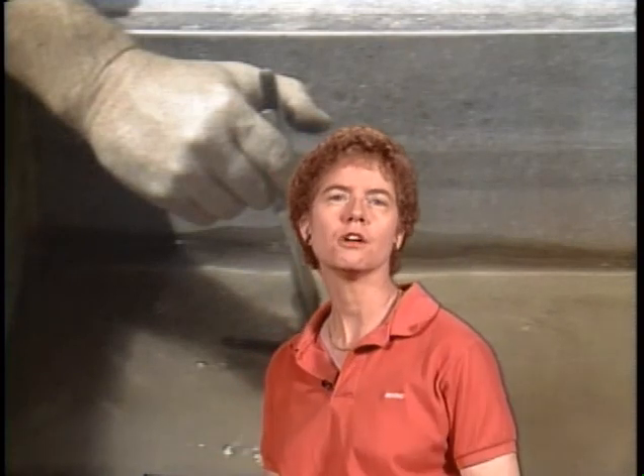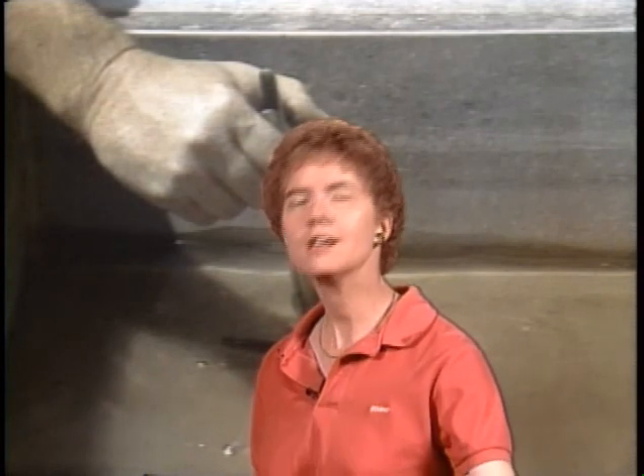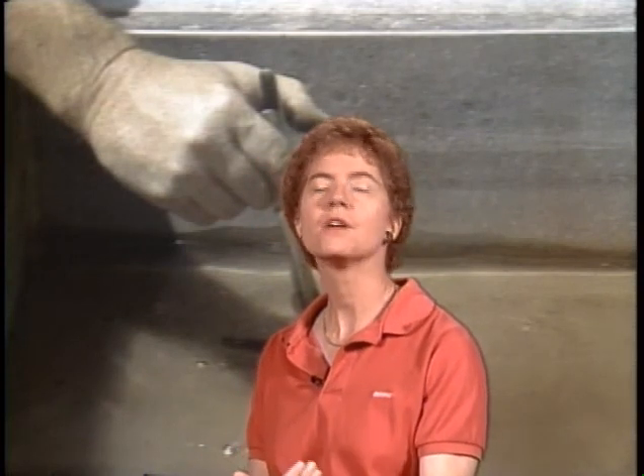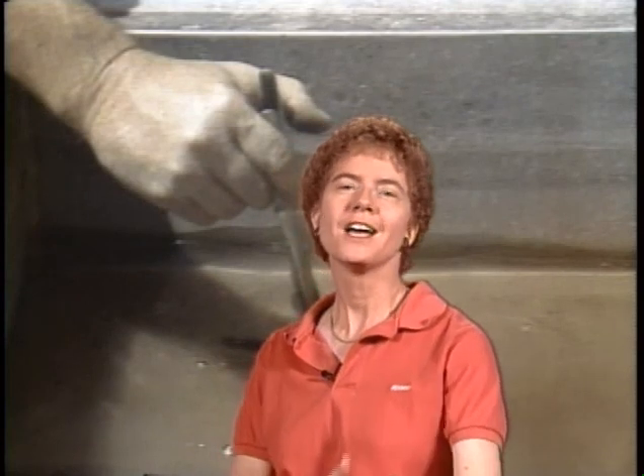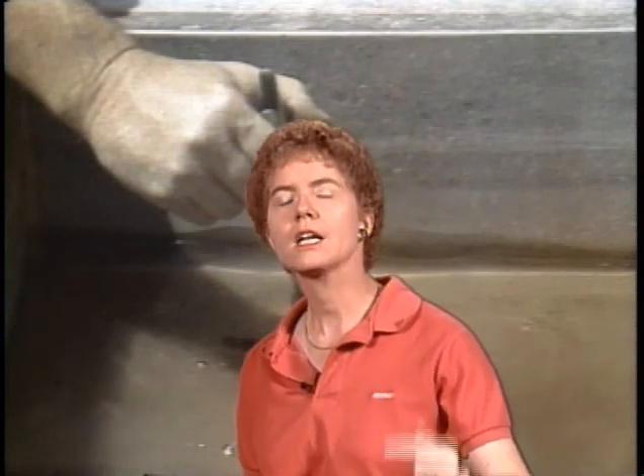Or they might say to you, if too much time is allowed to elapse during the transfer of an aluminum alloy, they may name it 2017, 2024, or they may just say aluminum alloy, from the heat treatment tank to the quenching tank, what could it result in? Well, if you let too much time elapse, it could result in impairing the corrosion-resistant qualities of the metal. Again, because if you don't quench it fast enough, the alloy grains will grow large, and the larger they get, the more likely intergranular corrosion is to occur.